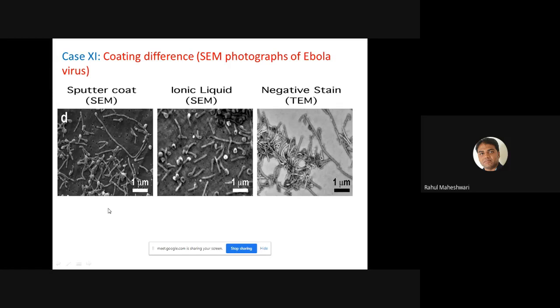So in this report, authors described the methods for concentrating the microbial suspension for the SEM observation on pre-coated filter substrate. If I'm talking about the sputter coating, it is pre-filter substrate. And they show that instead of sputter coating, an ionic liquid, what is the name of that ionic liquid that is now highly considered for the same analysis and replacing the sputter coating technique, right? It is 1-butyl 3-methyl imidazolium tetrafluoroborate,